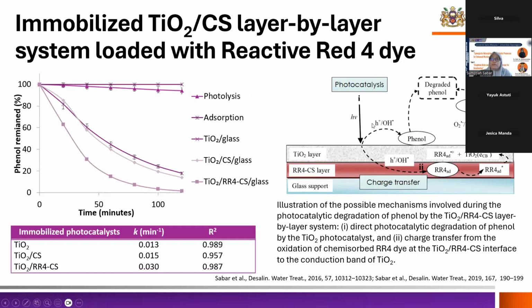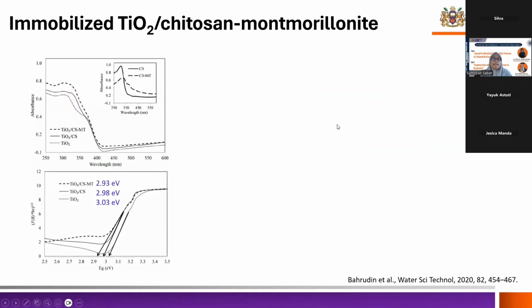Okay, so for the phenol degradation, there are only two mechanisms involved: direct photocatalysis and also the charge transfer from the oxidation of the Reactive Red dye onto the TiO2. So there is no adsorption occurring, but because of these two mechanisms occurring concurrently, it improves the degradation of phenol. Next, we try to modify the chitosan, because chitosan is not a porous material, it's a polymer. So it has a very compact, dense structure. And so we try to make it more porous